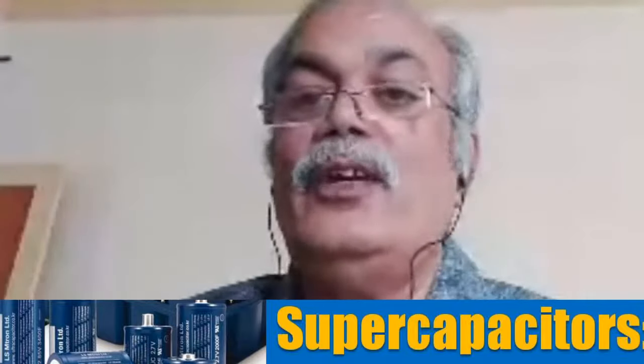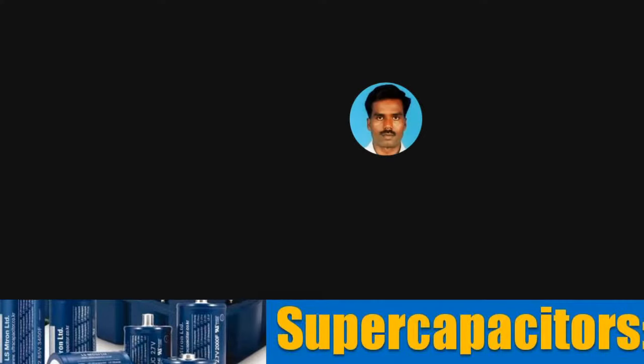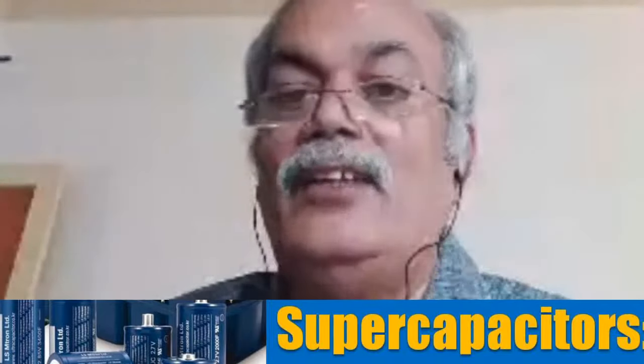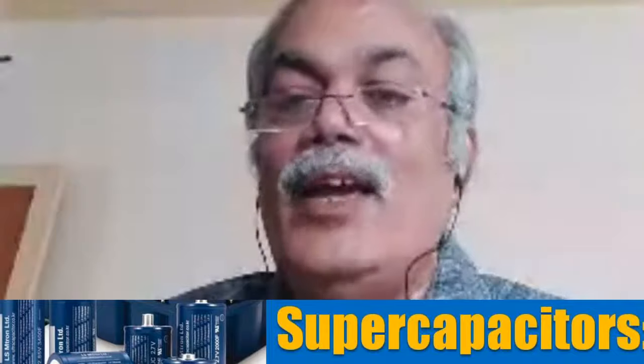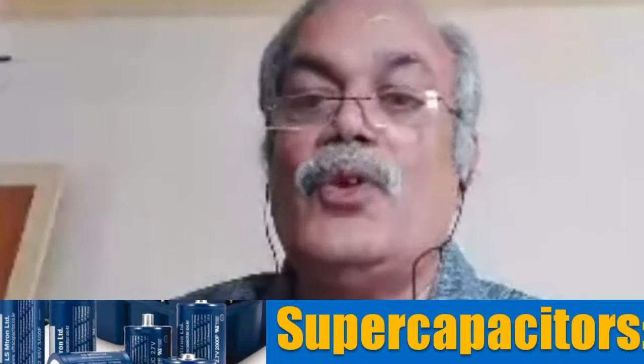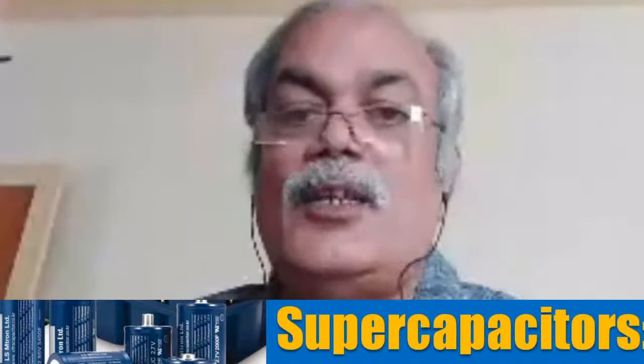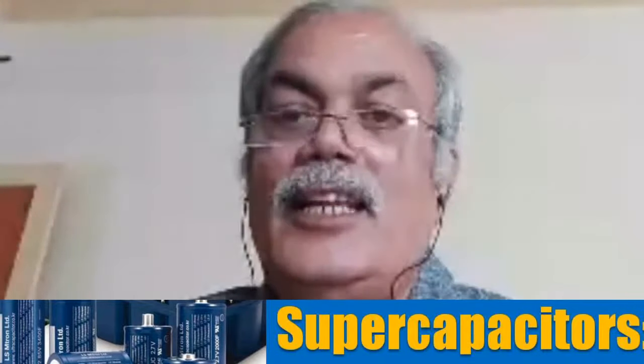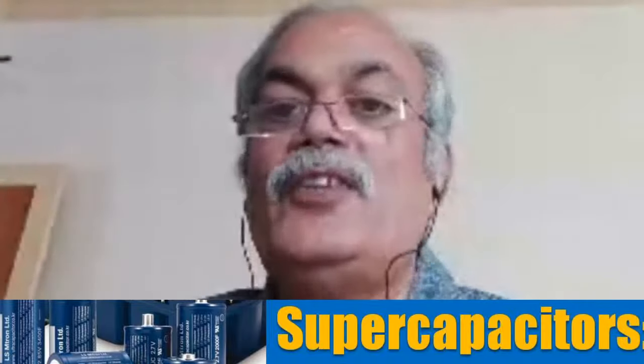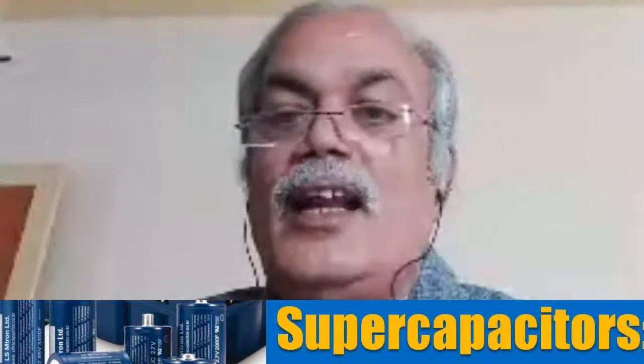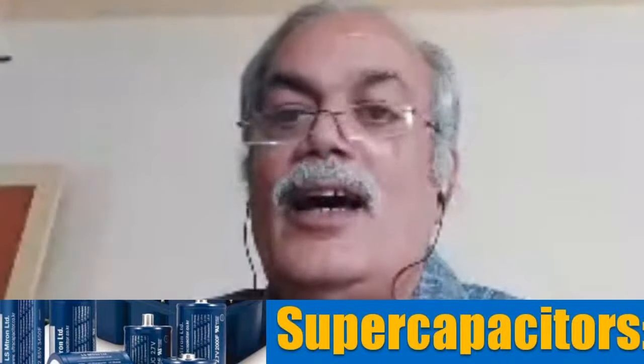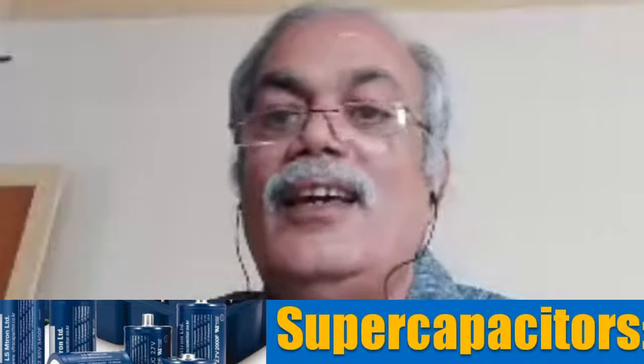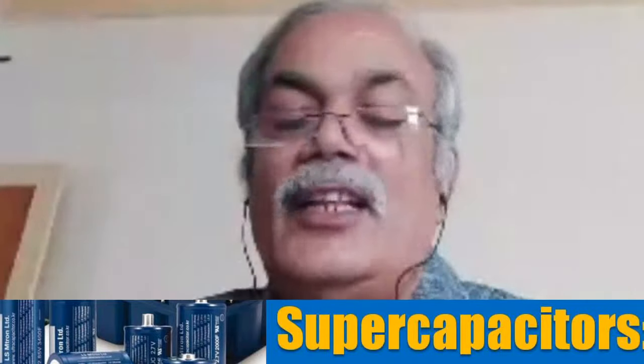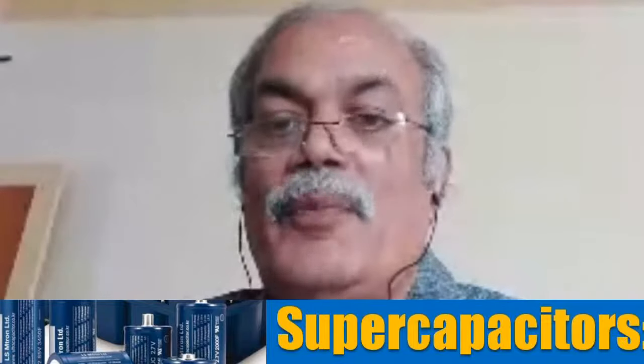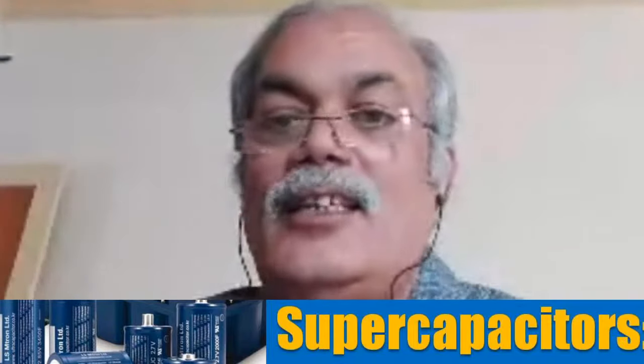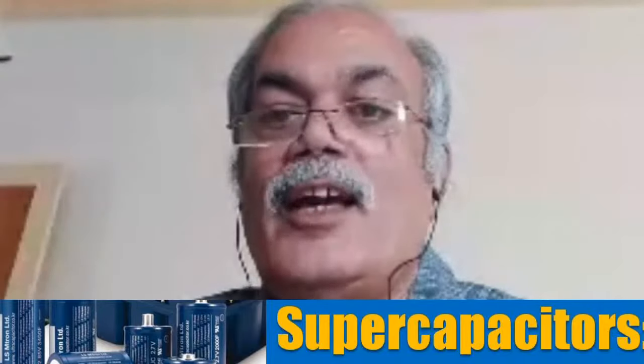As I was telling you, in regenerative braking, during the braking process, say about 5 to 6 seconds or even 10 seconds, the vehicle is retarding and comes to a stop. During this short period, a large amount of energy is generated by the regenerative generator, and this has to be charged. As I told you, a battery cannot accept, say, about 500 joules of energy in 2 or 3 seconds. The best choice will be the supercapacitor. So the entire energy regenerated during braking will be taken by the supercapacitor.